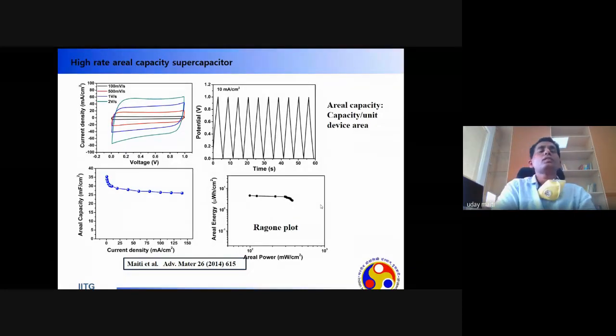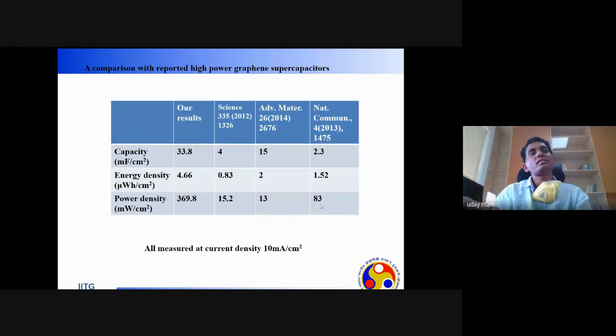Then we used it for supercapacitive energy storage, and we found that it can be charged and discharged at a very fast rate. Within some millisecond scale, you can charge it. And the areal capacitance is also very good. With the increase of current density, at 150 milliampere per centimeter square, if we charge or discharge at this rate, it still maintains a good capacitance. So this is good for ultra fast charging of capacitors. These are some metrics we have compared with other excellent papers.